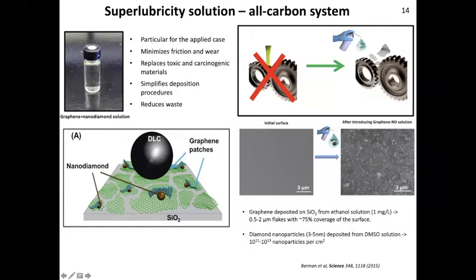The grayish areas are where we see our graphene flakes, and these white dots are diamond nanoparticles on the surfaces. If you observe the contrast, the graphene flakes are not covering the surfaces perfectly uniformly, not protecting all the surfaces. They have only a patchy, island-like structure. Diamond nanoparticles also have pretty good distribution on the surfaces, so we don't really see much agglomeration. They have pretty nice coverage of the surfaces. But again, we didn't try here to control what is happening. It was just sprayed on the surface, letting the carrier solution in the form of ethanol evaporate from the surface, leaving this coating behind.